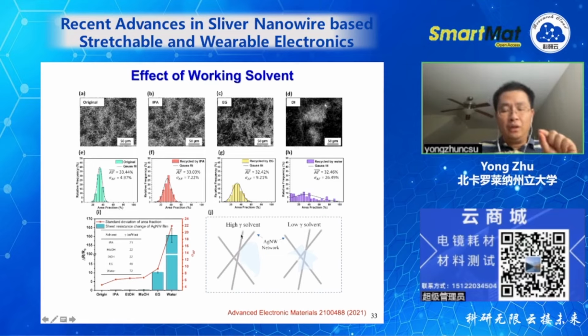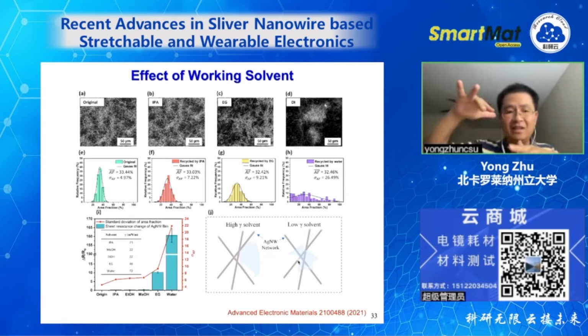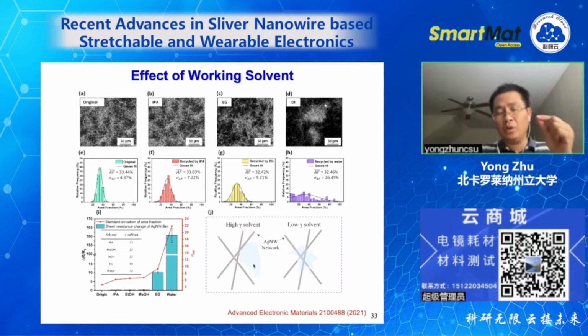So to put it short, why does IPA work better than DI water? It's because of the surface tension. IPA has low surface tension. With low surface tension, the working solvent can easily get into the junctions of nanowires, and then it can help to break the nanowires apart. But with high surface tension, it's difficult to get in, and then you cannot break the nanowire network.